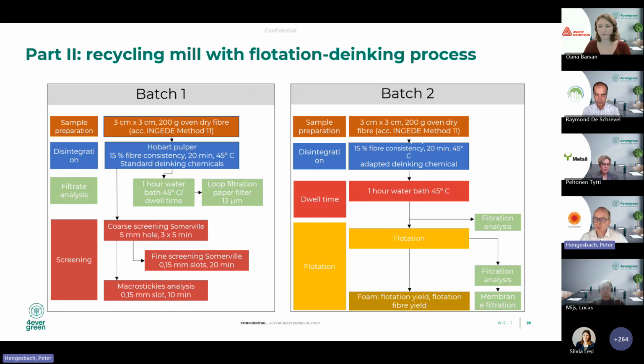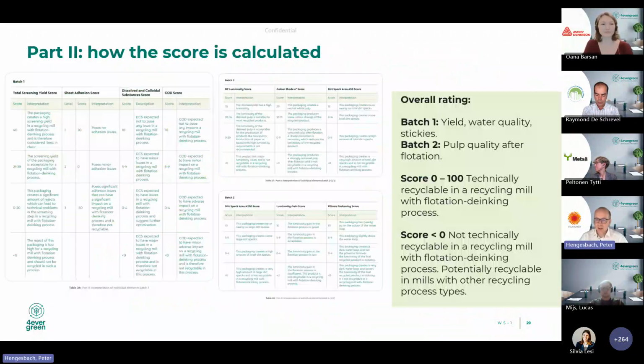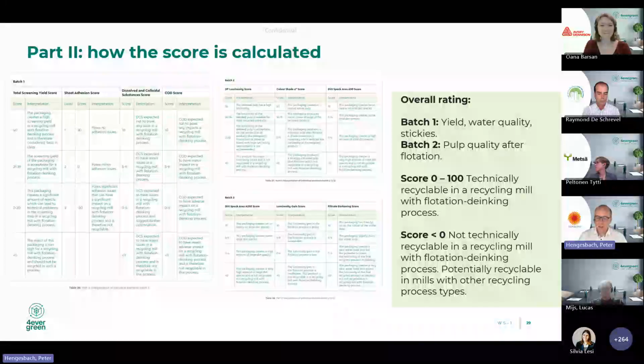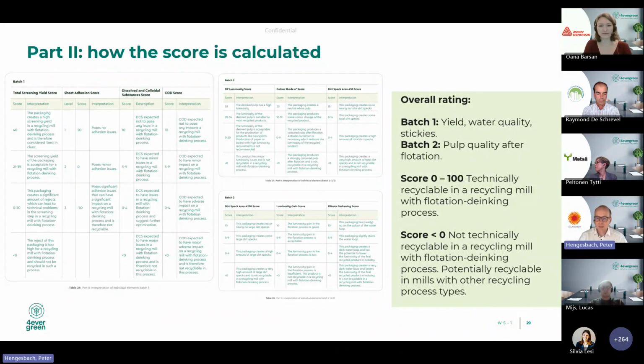And around those processes, of course, we are measuring quite some different parameters, which are used for the evaluations and for the results. I think you already noticed that there are quite some parameters, also shown in an earlier slide. So quite some parameters are considered for the evaluation. We have not reinvented the wheel, but we use the existing experience from the conventional process scorecard from part 1. But we also used existing assessment approaches for the flotation deinking of graphic paper, which has been established on European level as a harmonized method for quite a while. This is taken into account to finally summarize the results from the individual batches: for the first one, the screening and the reject analysis, and for the second one, the pulp quality after the flotation. Very similar to the conventional process, as you can see here.